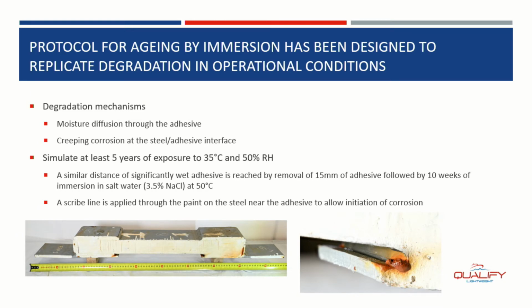Based on the calculations that Linda introduced, we found that the best approach to mimic this is, on the one hand, what you see in the bottom photograph at the left, to take away 15 millimeters of adhesive, and on top of that, to put this component into a saltwater bath, with 3.5% salt content in the water, at a higher temperature, 50 degrees Celsius, for 10 weeks of full immersion. That should allow the diffusion of moisture inside the adhesive. At the same time, we applied some scriber lines, also introduced by Linda, at the interface between adhesive and steel to allow potential creeping corrosion.